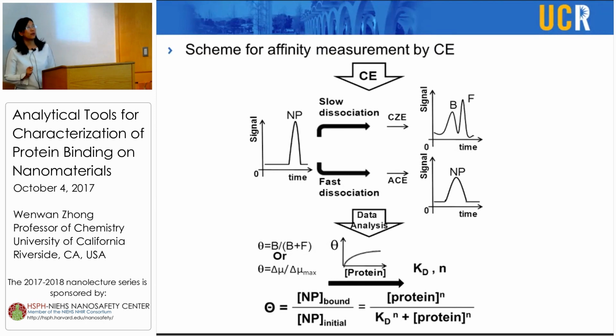Okay, thank you. So what we do is incubate the nanoparticle with protein, inject them into the capillary column, and apply an electric field to do the separation. What we see are two possible situations. One is that if the binding has a very slow dissociation rate, slower than the migration time, then we could potentially see a protein-bound nanoparticle peak versus a free nanoparticle peak. Then we compare the peak areas to calculate the bound ratio.